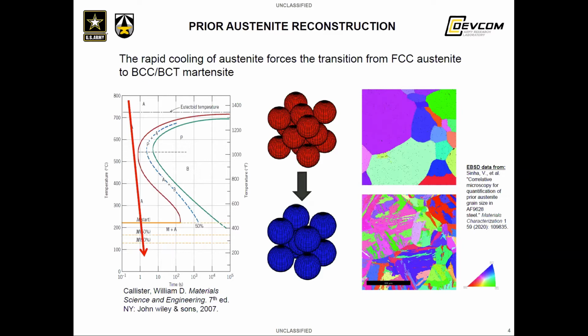So for those that aren't as familiar with steel, many of you will be, but by rapidly cooling face-centered cubic austenite, which is kind of the high temperature phase of steel, the material can transform into body-centered cubic or body-centered tetragonal martensite. And this happens through a non-diffusive transformation mechanism that we have labeled just the martensite transformation. Face-centered cubic austenite grains essentially shatter into a collection of martensite laths. This is kind of depicted in the images on the right, where on the top you have the austenite grain structure, and then beneath it you have the resulting lath martensitic structure.